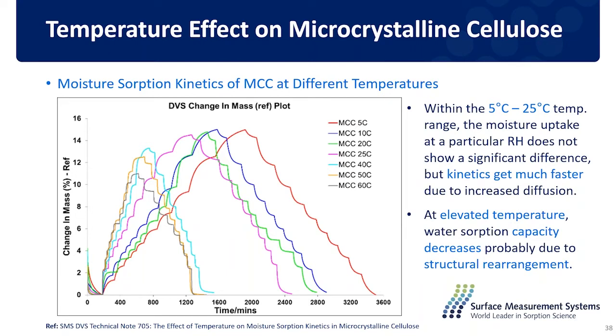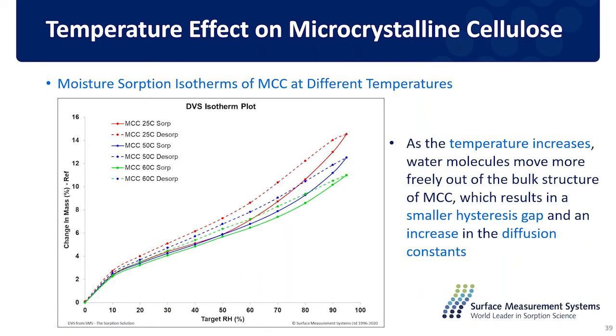So with the DVS technique, we can easily detect what the moisture content or water sorption capacity of the material is at different temperatures, and how the temperature affects the moisture sorption kinetics from the mass plot. The same we can also compare in the isotherm plot. What we notice here is the water capacity is dropping at 90% RH with increasing temperature, and also the hysteresis gap between sorption and desorption branches is becoming smaller as well, because the diffusion of the water molecule is faster at higher temperature.